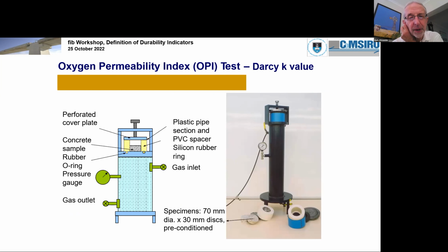So this is the OPI test, the Oxygen Permeability Index test, that was developed in the late 1990s. It's a very simple test. It's a falling head permeameter in which a specimen is clamped into a specimen chamber. One charges the cylinder with gas, oxygen in this case, measures the pressure decrement with time, and within the space of not more than 6 hours, you get a result which is related to the Darcy coefficient of permeability.